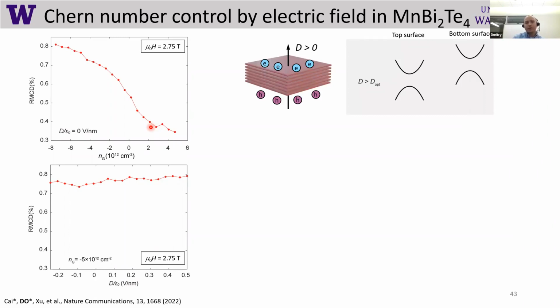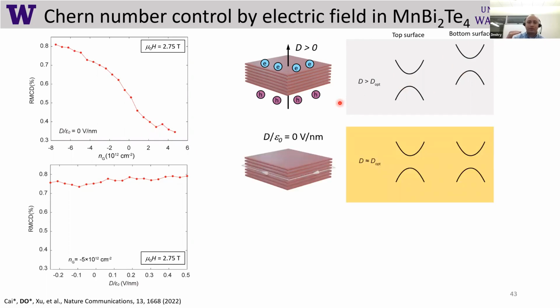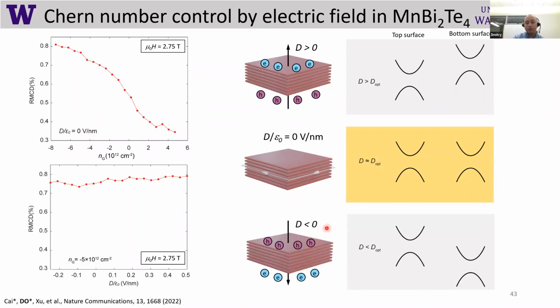So instead, what we understand is happening is that electric field aligns the top and bottom surfaces. When we have an imbalance between Fermi levels on the top and bottom surfaces, we cannot get Chern number 1, and we need really fine tuning of the top and bottom surface Fermi levels to get to the optimum electric field. And that allows us to now develop an edge state. So we essentially electrically tune Chern number in this material by controlling the top and bottom surface. And for the lower electric field, negative electric field, the same situation is in place. When you misalign them, you don't have an edge state anymore.